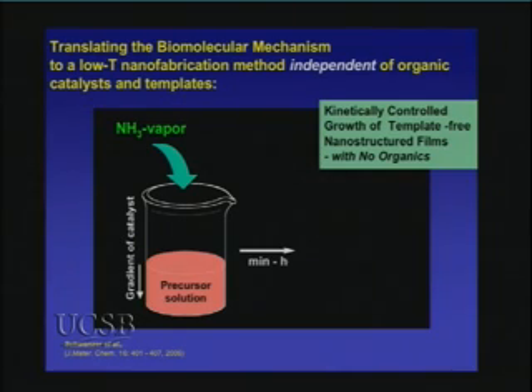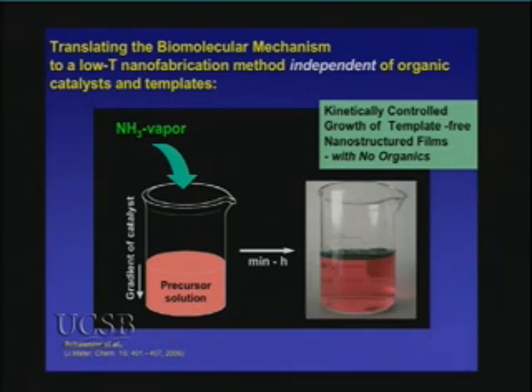We start by diffusing a catalyst from the gas phase through the meniscus of a solution of a molecular precursor that must first be hydrolyzed before it can undergo condensation to form the network of either glass or metal oxide semiconductor. Because the diffusion is slow and establishes a gradient, that vectorial control of increasing concentration as a function of space and time through the solution, we get the growth of metal oxides and hydroxide semiconductors without any organic template, no biochemicals, no polymers are needed.